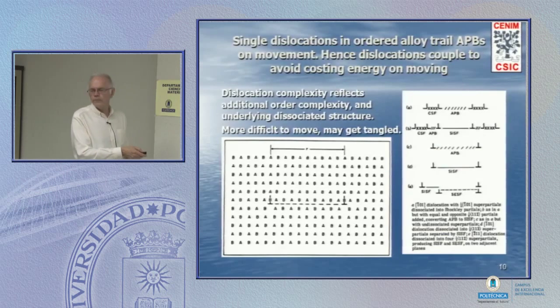Now there are various types depending on the precise crystal structure and what sort of stacking fault. It's very much the equivalent of two Shockley partials with a stacking fault in between. The type of dislocation I get depends on the precise crystal structure, but in all cases the core of the dislocation is now not a point object, it's a planar object. You can think of it as a ribbon in three-dimensional space, which means it's more difficult to change plane. Things like cross-slip, moving a dislocation over an obstacle, is more difficult.